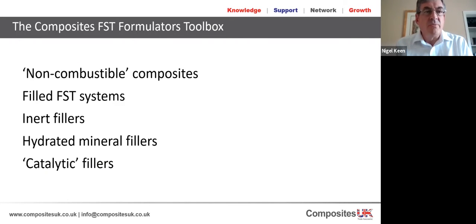So we've got, in our toolbox, a whole number of different things. We can go non-combustible. Non-combustible composites might be things like ceramic matrix composites or metal matrix composites. We can use quite brittle matrices. We can use cement and have a basalt system, for instance, or a glass system. So we can create composites where the matrix is quite brittle and the fibers provide toughness or impact resistance. And we can create non-combustible composites in that way. Composites can have very low organic content, and you can actually pass some non-combustibility tests doing that.